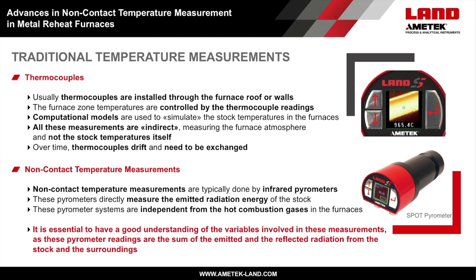And such thermocouples may have a drift and need to be exchanged over time. The main advantage of non-contact temperature measurement is that this method allows to measure the direct object surface temperatures. It's typically done by infrared pyrometers, measuring spot temperatures, or thermal imaging systems, measuring whole thermal images with thousands of measuring points or pixels. By choosing the right spectral response, the non-contact temperature measurement is independent from possible influences of hot combustion atmospheres.